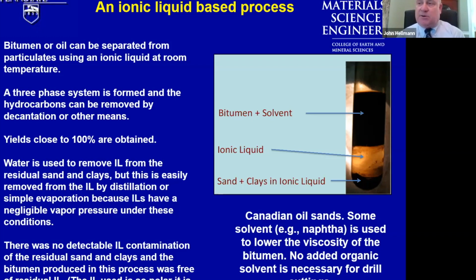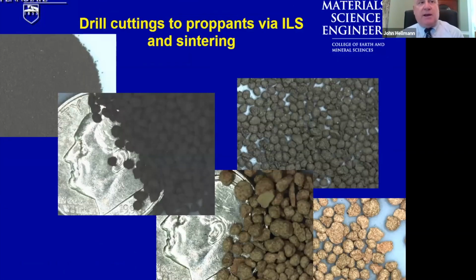The ionic liquids can be separated from the powder particles via a water wash, which is great environmentally sensitive. The ionic liquids are recyclable and containable, also environmentally desirable. And so we were able to manufacture aggregates from the drill cuttings that were produced from the ionic liquid separation process. These are showing some of the aggregates before and after sintering. This preliminary work demonstrated that we're able to make aggregates that are moderately high strength, should be useful for aggregates for construction as well as for propping gas wells with more development.